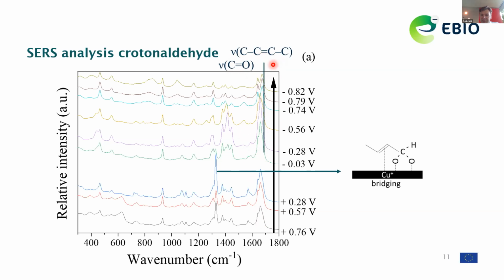crotonaldehyde on the surface in comparison to the butyraldehyde, which, remember, in the previous slide I showed there were hardly any spectral intensities visible. So there is a very strong preference for the copper surface at negative potentials to have this double bond adsorbed on the surface, and that explains the surface specificity for this reactant, the crotonaldehyde, in comparison to the butyraldehyde. Interestingly, we still don't fully understand that the double bond, even though it interacts strongly with the surface, doesn't really get activated to hydrogenation.